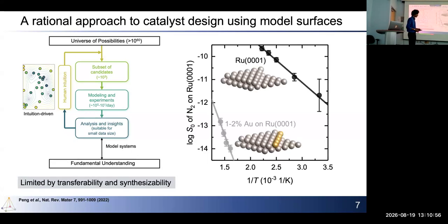So to give an example of what this looks like, here is the same reaction that I was mentioning earlier about nitrogen dissociation. How does nitrogen react on surfaces? So you could take a really well-defined ruthenium 0001 surface. This is one of the flat surfaces, and you can see the reaction rate here. And then the hypothesis is that it is these step sites that are responsible for generating the catalytic activity. So the turnover frequency that you see here is because these atoms are the ones that are responsible for nitrogen dissociation. And the way you would test this hypothesis is you could selectively deposit gold atoms next to these ruthenium sites to block them. And then you see a tremendous drop in activity.